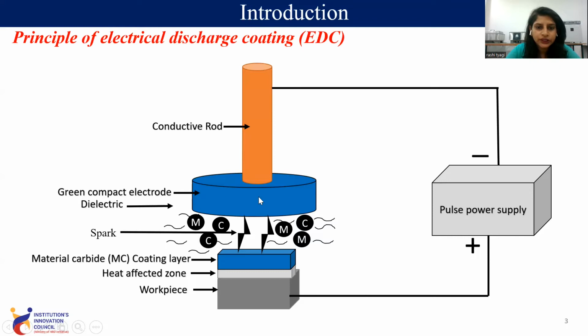Electrode, as you can see, this is the green compact electrode, which has a loose bonding between its particles because it is made from the powder at a low compaction pressure and temperature. As we have compacted the powder, then we have made this compact, so it has loose bonding between its particles. So it becomes easy to deposit the workpiece surface by utilizing the spark discharge in EDM. Basically, reaction takes place between material that comes from the green compact tool, the dielectric.